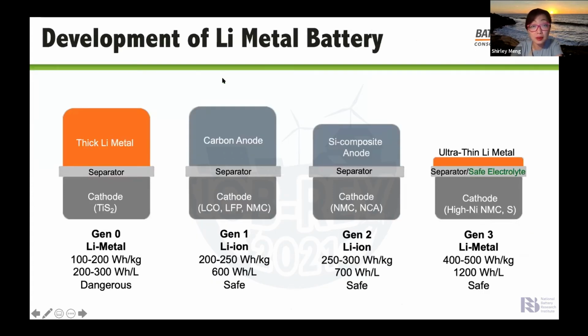So the development of the lithium metal batteries has not been a very straight pathway, because in the 1970s and early 80s, lithium metal was explored as a promising anode material, but at that time our cathode materials do not have lithium in it. Today, with the high nickel NMC, we can afford just to have very thin lithium in the anode side, because there's a lot of lithium in the layered NMC materials.